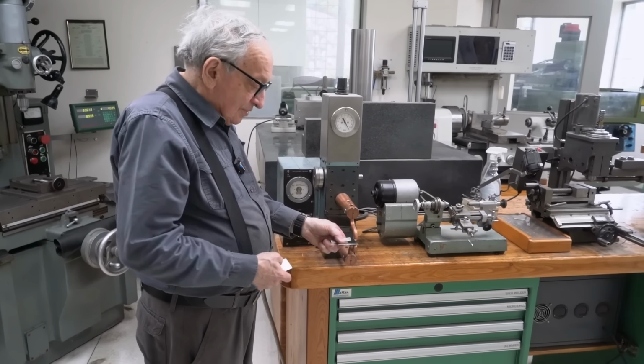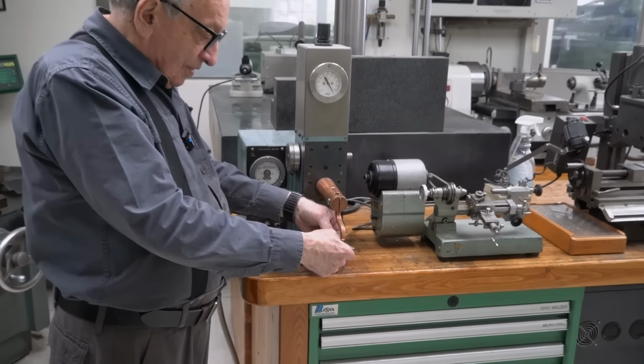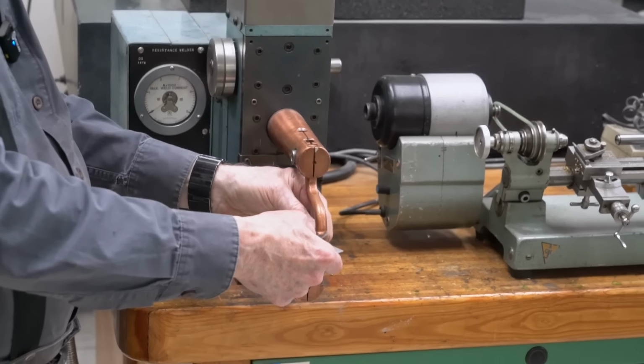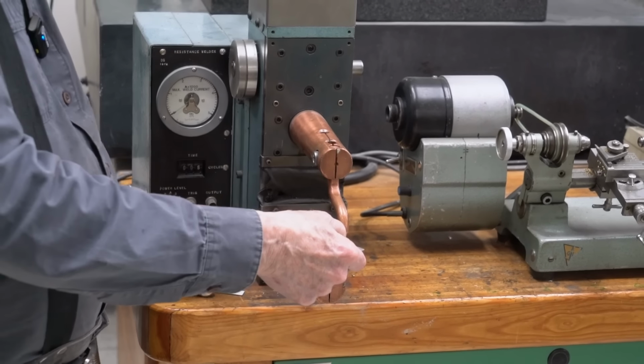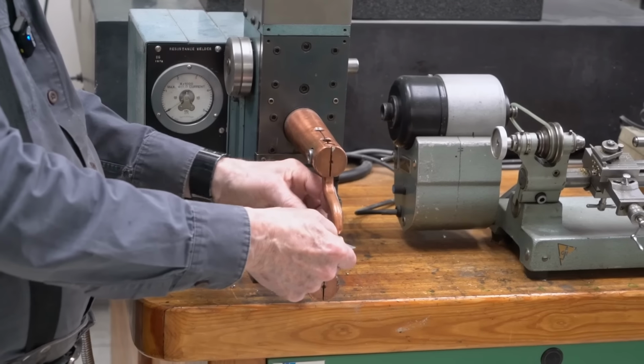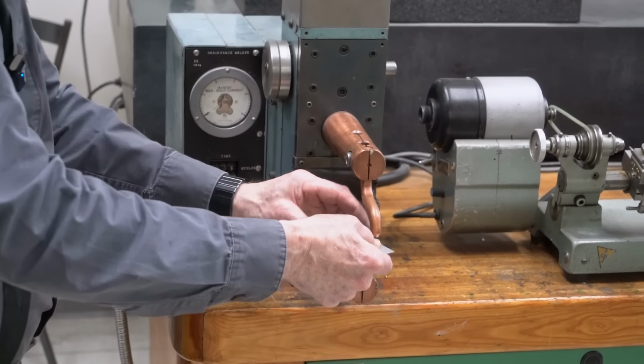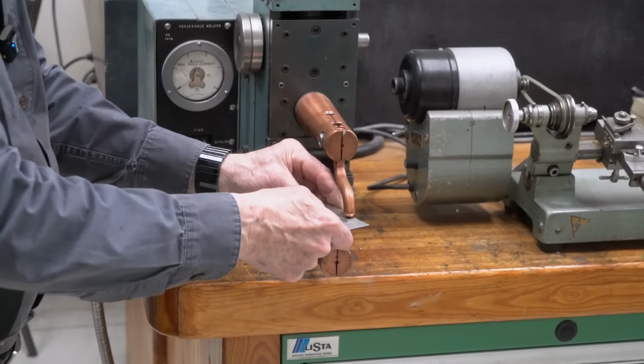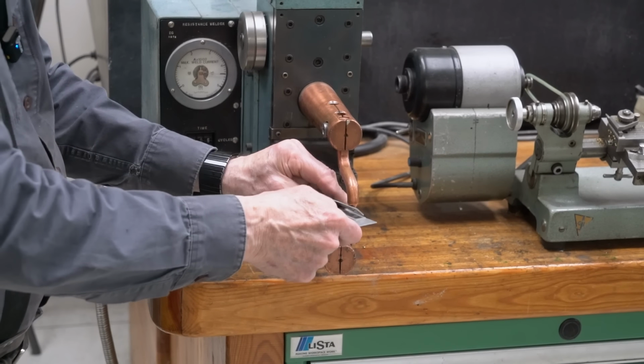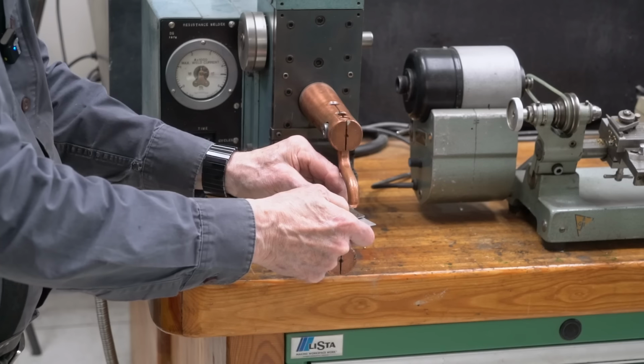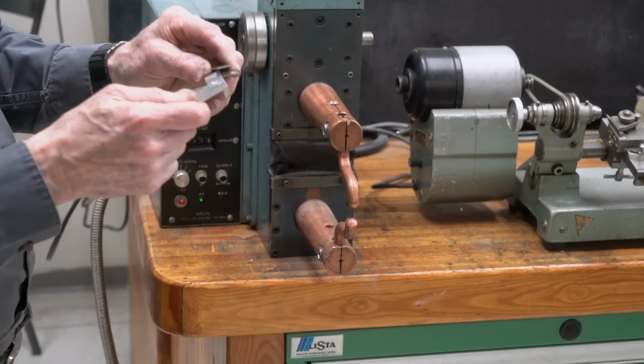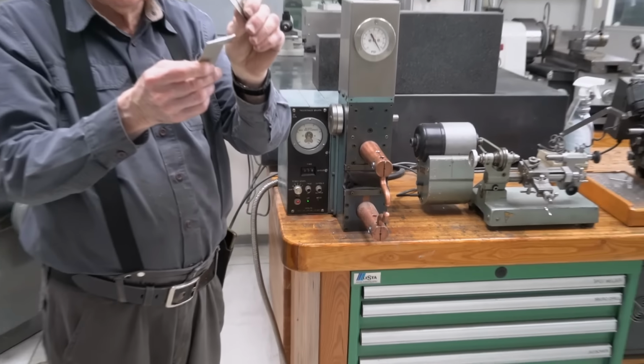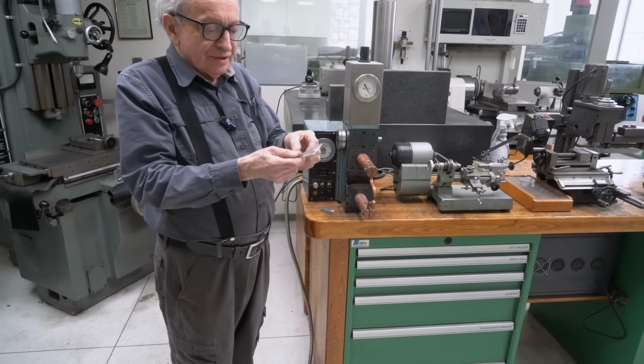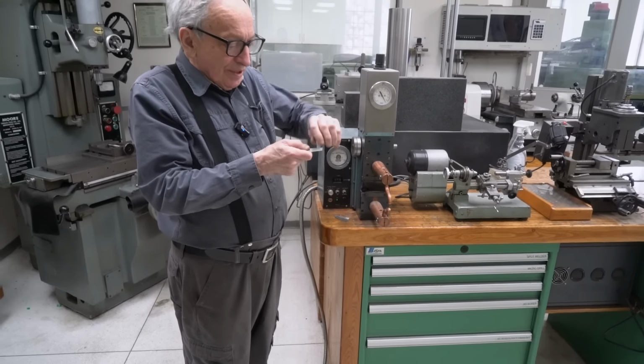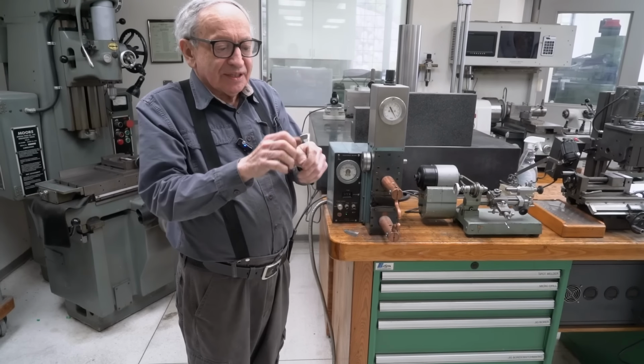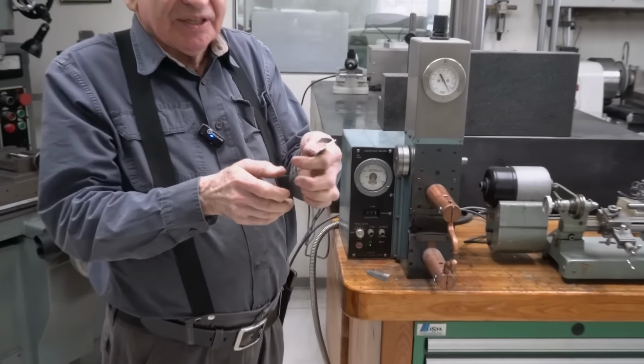So you put down a piece of stainless steel, you put down aluminum, you put down the second piece of aluminum you want to weld, and you cover it with another piece of stainless steel. So the aluminum is sandwiched between 2 pieces of stainless steel. And now you can weld. Do another weld. So, okay, the stainless steel doesn't stick to the aluminum, but the aluminum is nicely welded, and if I bend it, you can see that it doesn't come off. See, I cannot get it off.